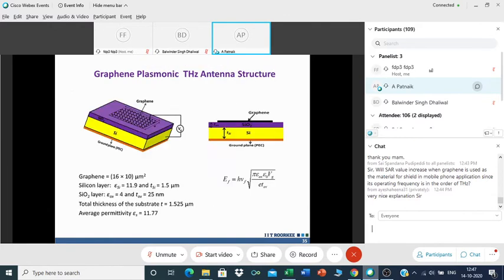So we made a simple graphene antenna structure. What is that one? It's a silicon layer. Above that, a silicon dioxide layer. And the graphene layer is sitting on that silicon dioxide layer. And you can mark the cross section in this particular figure. So when you apply a voltage across this graphene layer, you can see this particular expression: EF is dependent on VG.